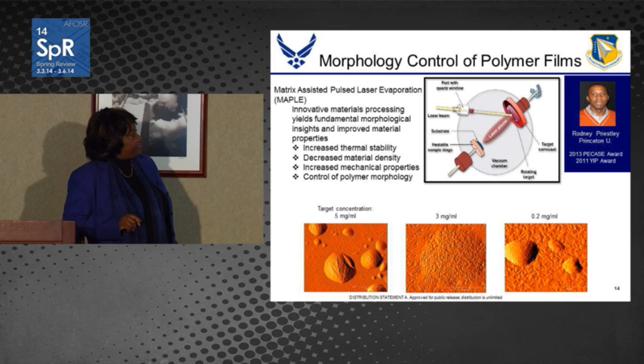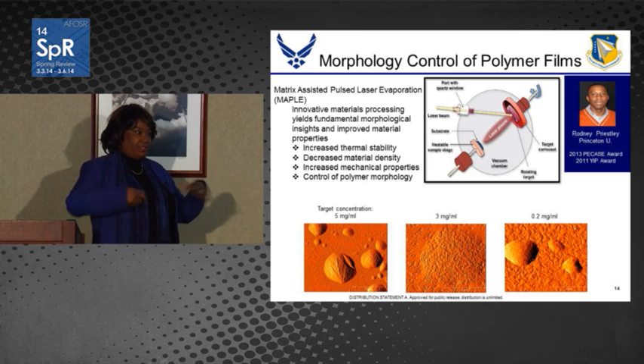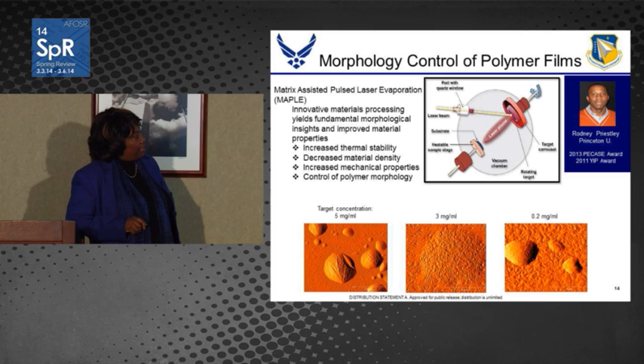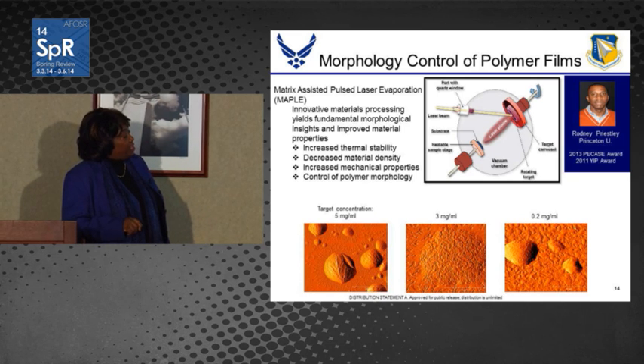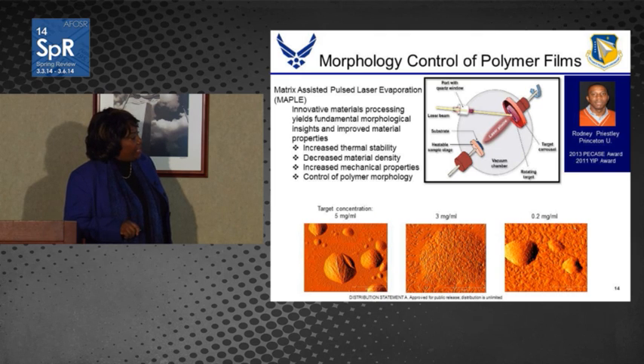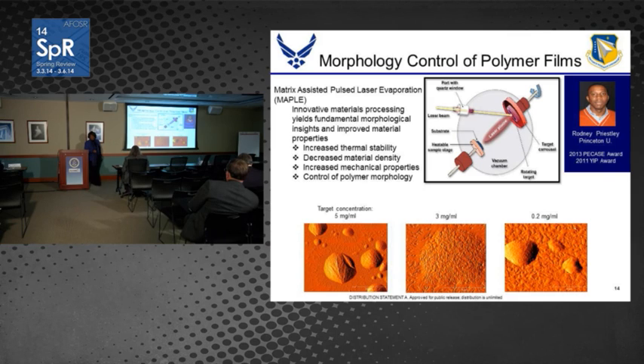And so when the incident laser beam hits that, you create a plume that has this highly volatile solvent that just evaporates off, and then you end up with a very thin layer where you can begin to control the thickness and a lot of the properties of this thin polymer on the substrate. And so Rodney is using this method to really study and control polymer formation and morphology formation in these polymers. This here is just one example of how you can control any of the parameters here, such as target concentration, and create a very large range in terms of the morphologies and this so-called nanoglobule formation that you get, which leads to drastically different properties in these materials.